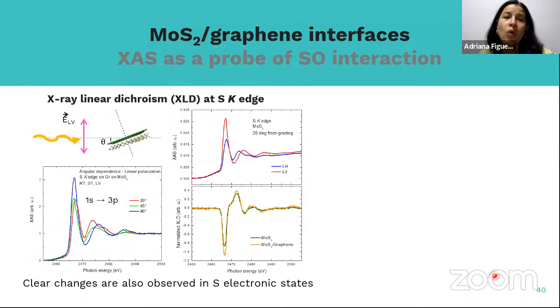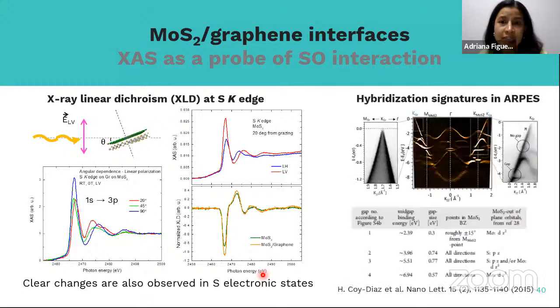And then also, if we tune the energy to the sulfur K edge in the MoS2, with and without graphene, we see changes that are also observed at the sulfur electronic states, and they agree with those results of hybridization. And this is also something that has been reported by angle-resolved photoemission spectroscopy measurements, when they have observed hybridization of these orbitals in graphene as a result of the proximity to MoS2.